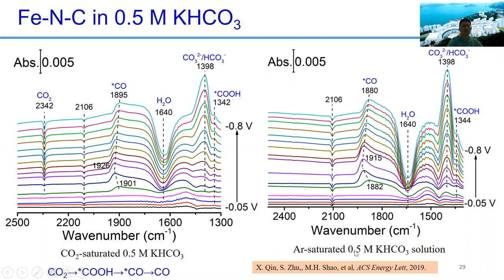And with argon saturated ones, the bands are similar, but the only difference is that you don't see this carbon dioxide because you don't have the carbon dioxide here. But you still see this carbon monoxide because it comes from this electrolyte. So the reaction pathways supposedly follow those on the metals: CO2 adsorbed on the surface to form *COOH, *COOH decomposes to *CO, and CO removes from the surface.